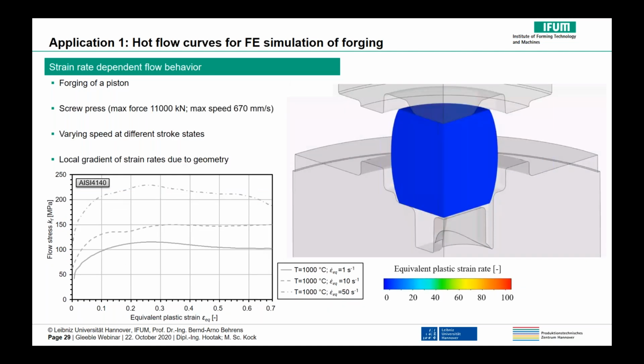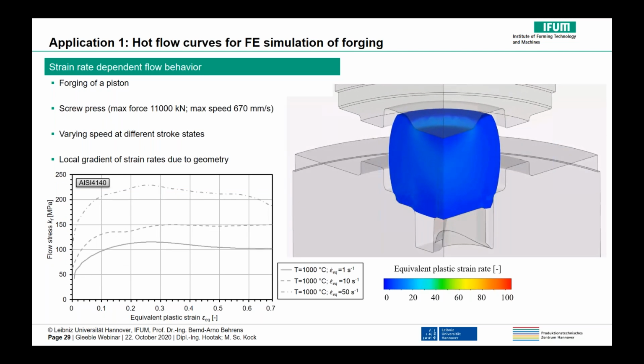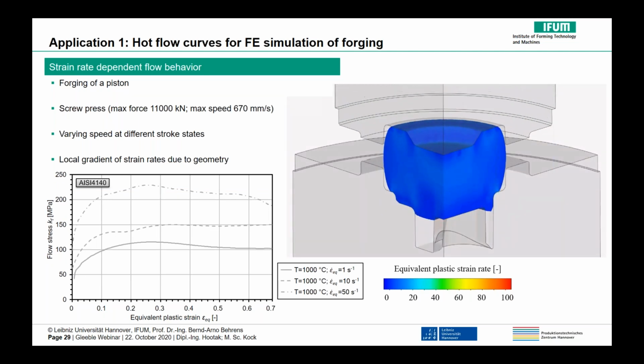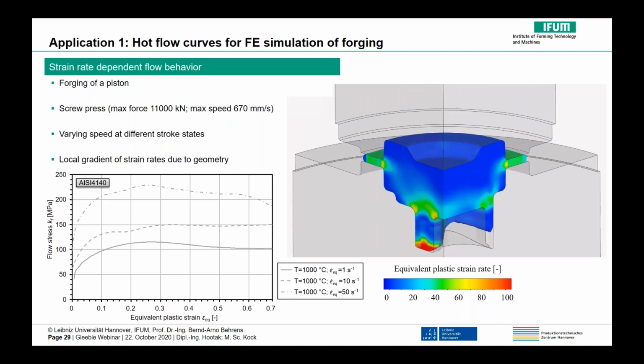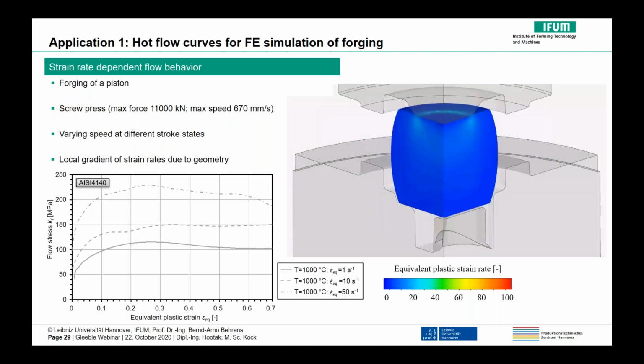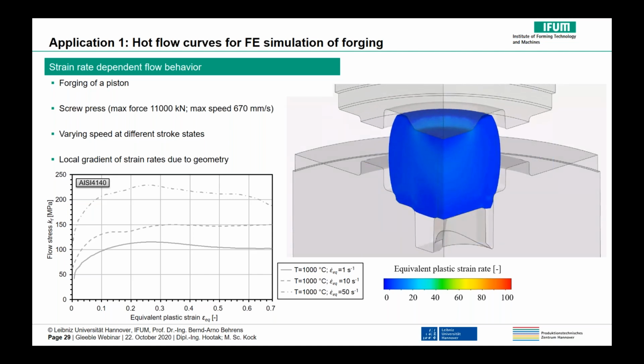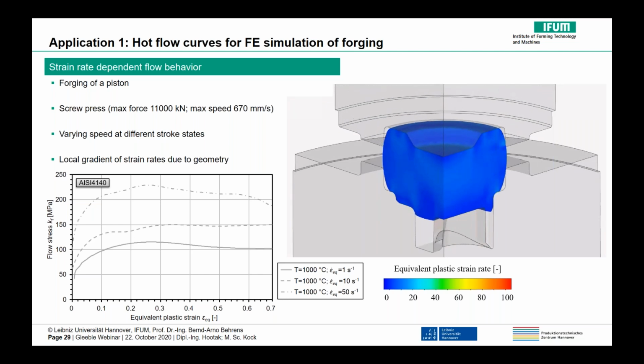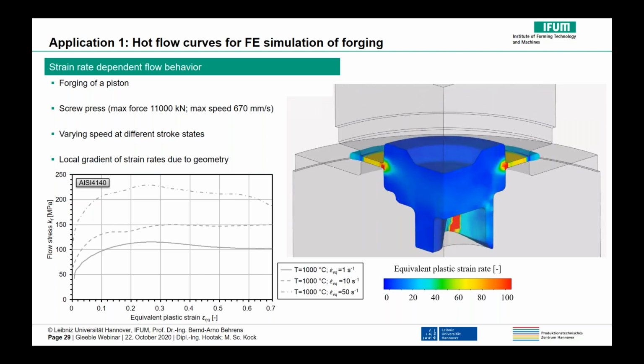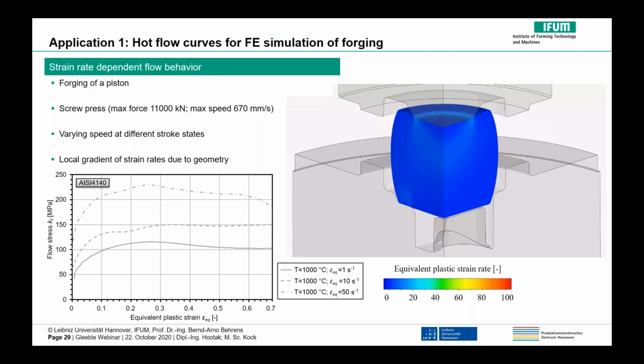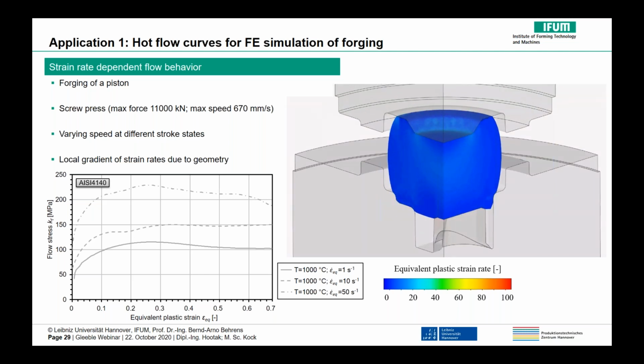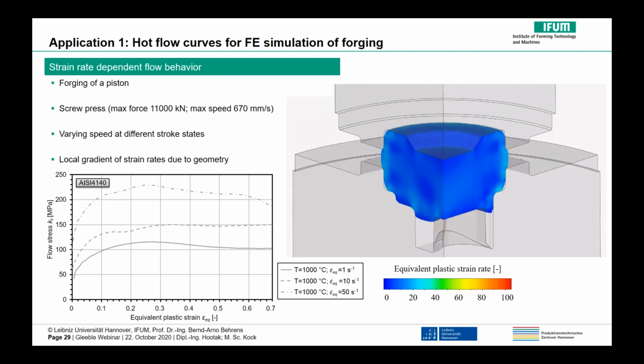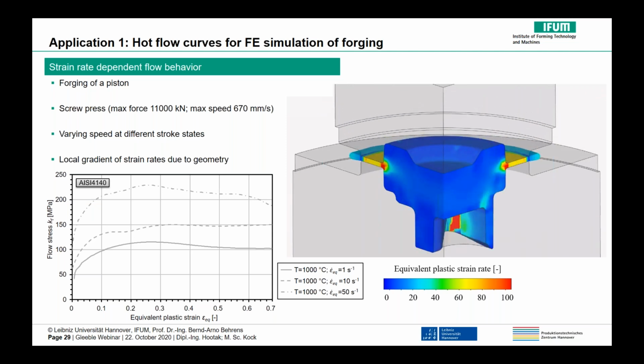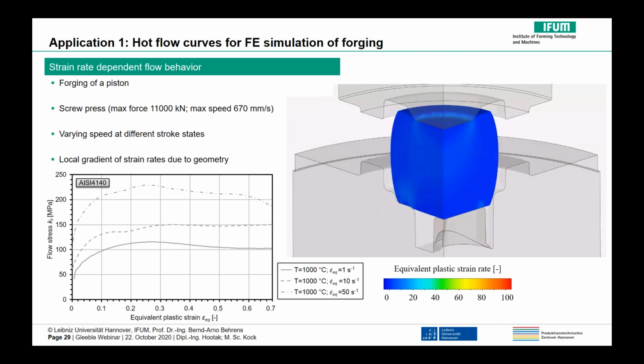In the same way, we can calculate the strain rates that occur in the material. In this model, a screw press with a maximum speed of 670 mm per second is considered. The video shows that local equivalent plastic strain rates of more than 100 per second occur in the component. Again, the strain rate gradient results in locally different flow conditions, as shown by the flow curves determined in Gleeble.